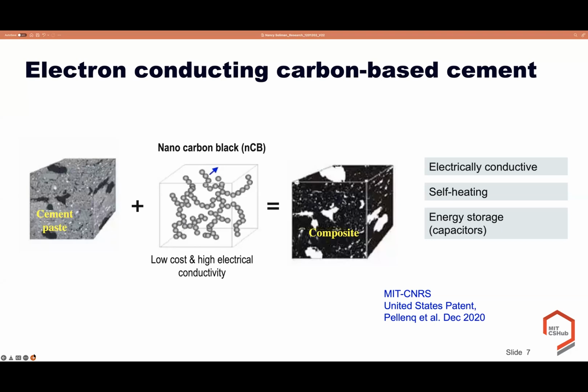And here I will present the development of electron conductive cement-based material using nanocarbon particles by changing the microstructure of the cement matrix. When we add nanocarbon black into the cement matrix, we develop a novel composite that has electrical conductivity, self-heating, and energy storage. And this is a patent between MIT and CNRS.